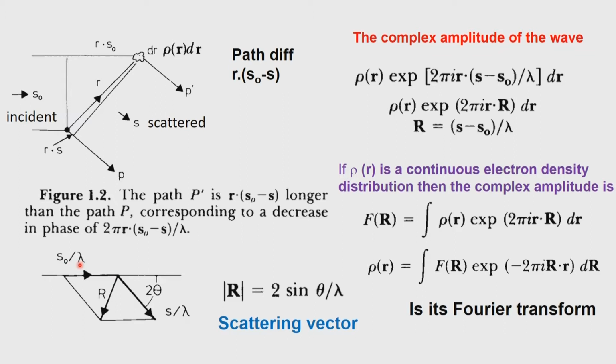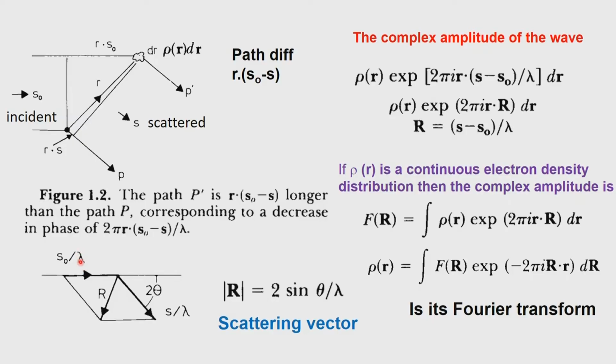Remember that we are talking about atom sizes of the order of 1 angstrom. So, the wavelength can be anywhere between 0.4 to 2.5 angstroms. If we use that wavelength, we will be in a position to see the details associated with atoms and molecules and so on. So, we prefer to use X-rays in that range, about 0.5 angstroms to 2.5 angstroms. Since lambda is coming up as a normalization factor, it is recommended that we use a single wavelength.